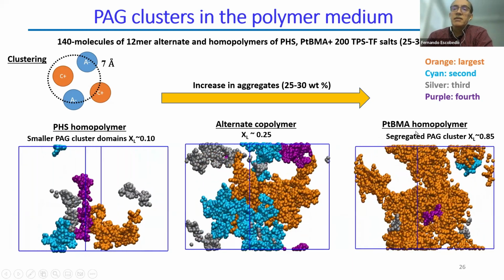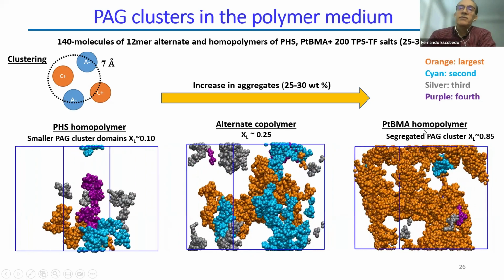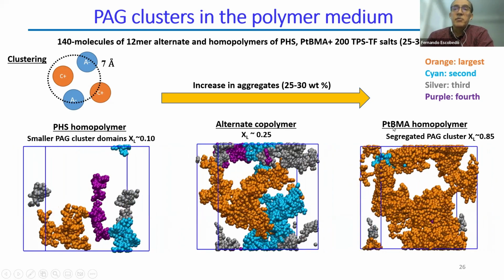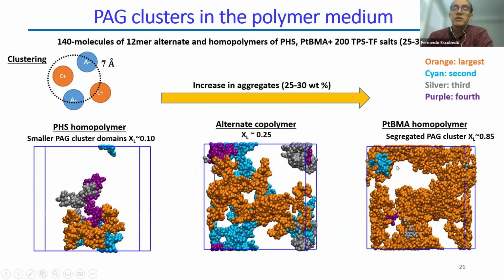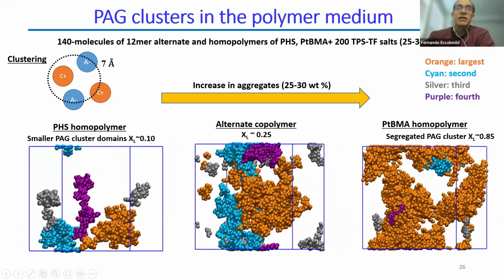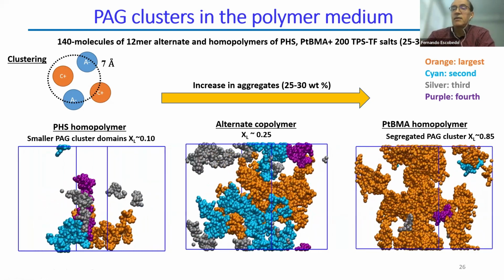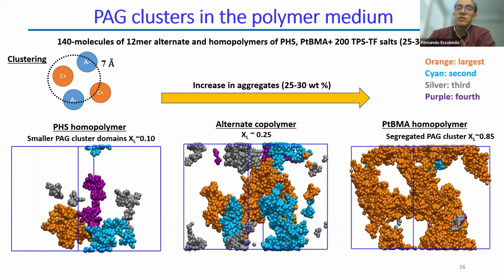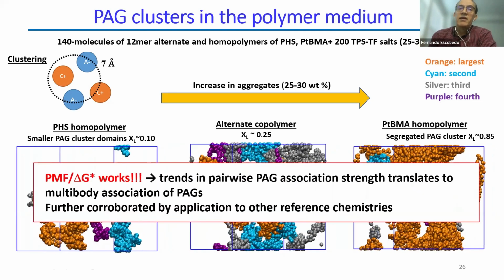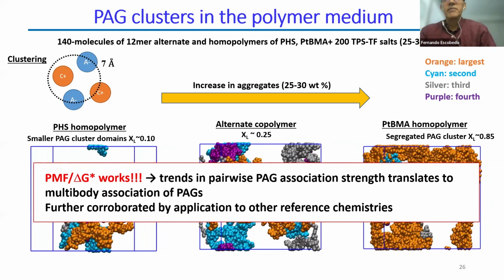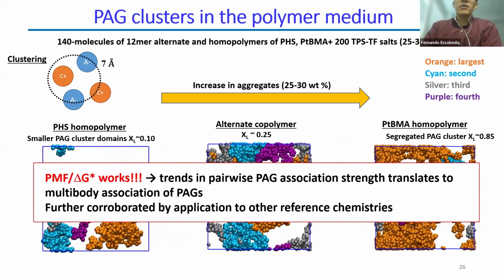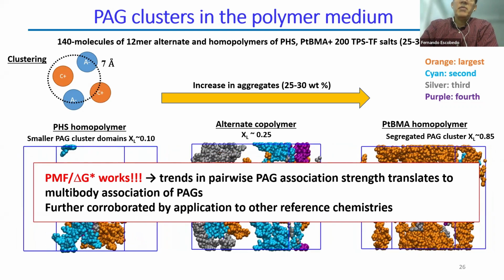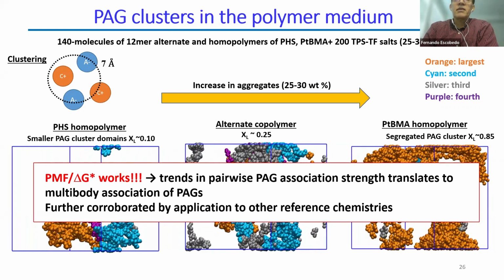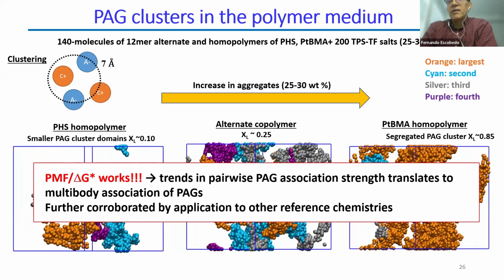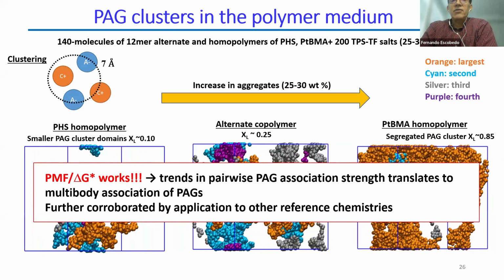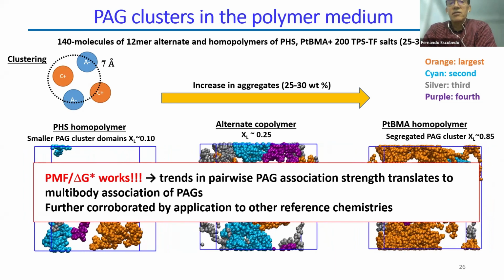But clearly, areas of your system where you have a high concentration of PTBMA will not be appropriate, because it will create these large clusters and likely translate into large roughness at the end when you produce the features from this photoresist. But importantly, our hypothesis that you can extrapolate things based on the PMF delta G star works, right? Those trends in pairwise association strength translate into this multi-body association of PAGs at high concentrations.